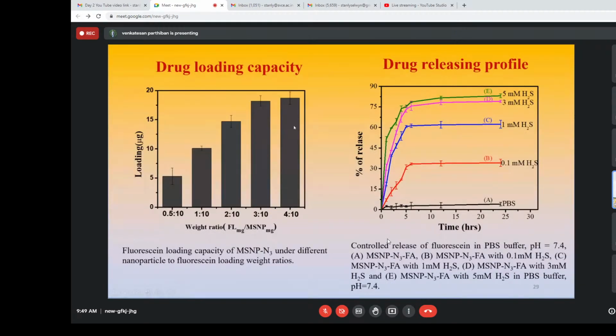Further, we check the pore volume of the mesoporous silicon nanoparticle as a high drug loading capacity carrier, right? So we use this strategy in a drug loading capacity experiment. We can see here we use ratios like 0.5 and 10 to check the maximum drug loading capacity. So this one, the 3:10 ratio, is the maximum. Further, we check the drug release experiment also.